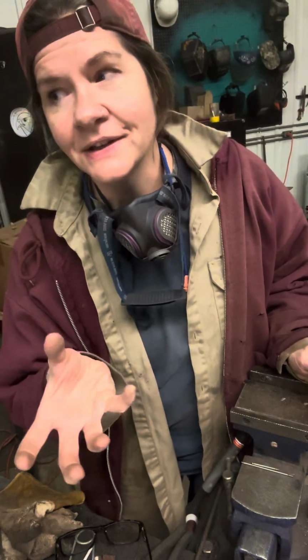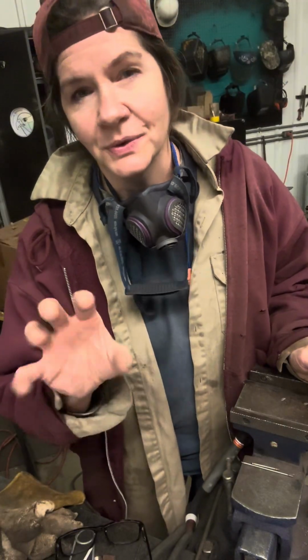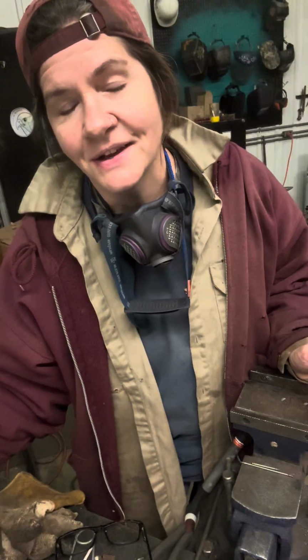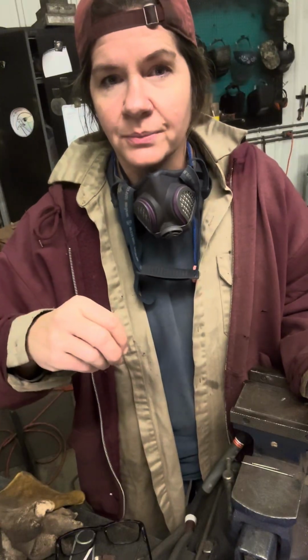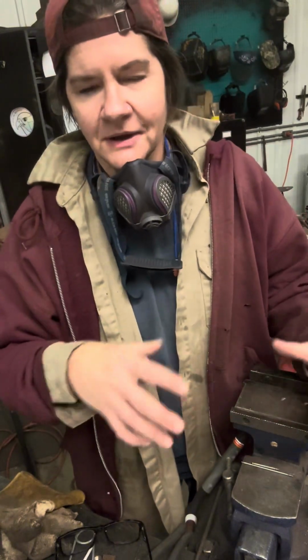Crater cracks, or end cracks, or sometimes shrinkage cracks, or star cracks, or stars, but my favorite term is assholes, and that's pretty much an industry standard. They occur when you're welding along, putting in a bunch of heat and a bunch of material, and you just break it off, and you don't fill the very end of your weld with a little bit of material, and you break off the heat very quickly. So rather than having a slow gradual cooling, it's all trying to cool at once, and as molten metal cools, it shrinks.